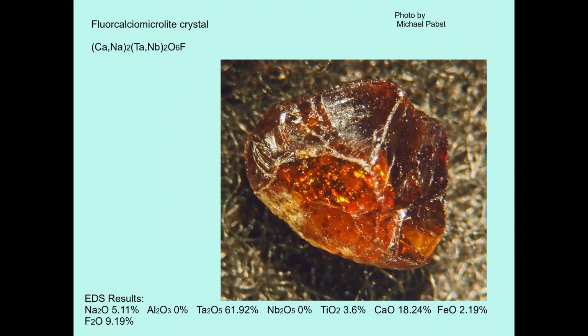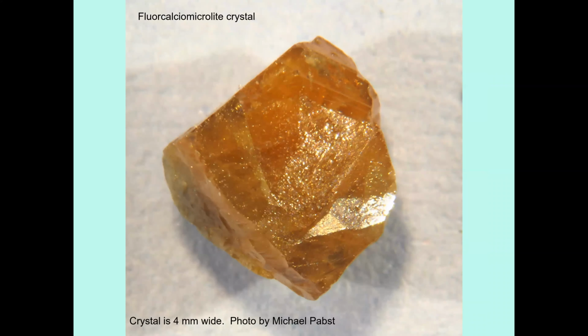This amber red variety of fluorocalcio-microlite was also extremely rare. Interestingly, this sample registered the highest fluorine percentage by far of any sample tested. Next slide. Yellow varieties were also very rare, and several samples not pictured here were tested for possible evidence of another microlite group species that may have occurred in the pegmatite, fluornatromicrolite. The results were inconclusive. Next slide.